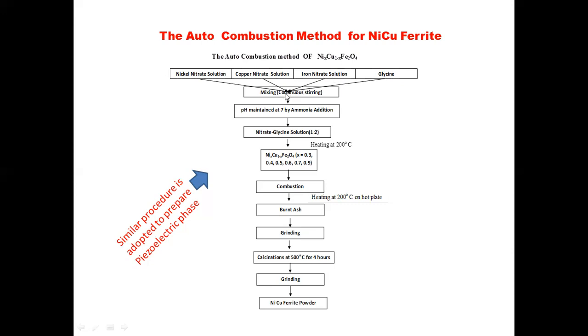Here the beaker should be at least 1000 ml, because once the burning starts, the burning solution may come out of the beaker or rush out suddenly as it expands, which is very dangerous. That is why you have to take at least a 1000 ml beaker to mix all these things.